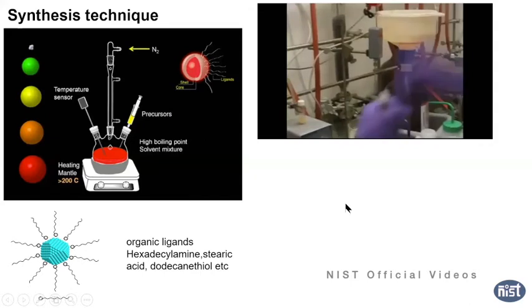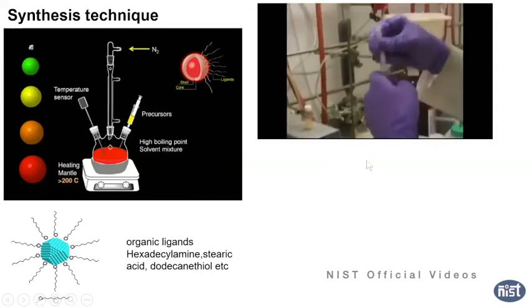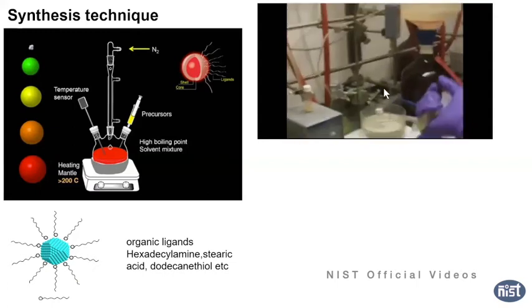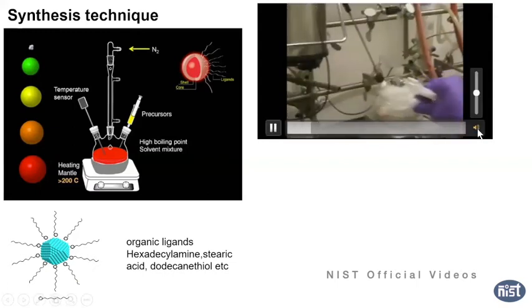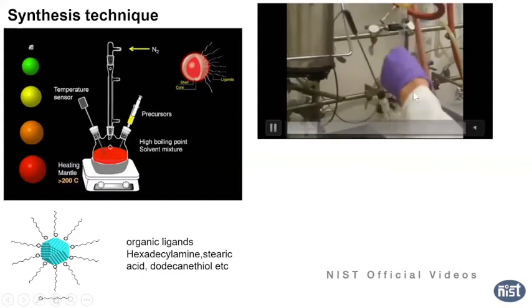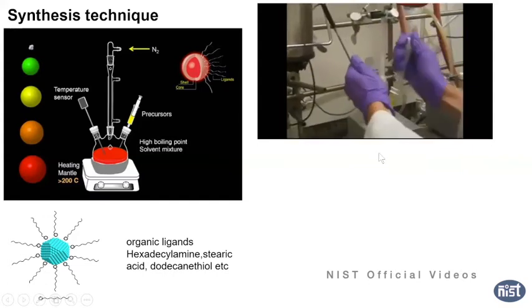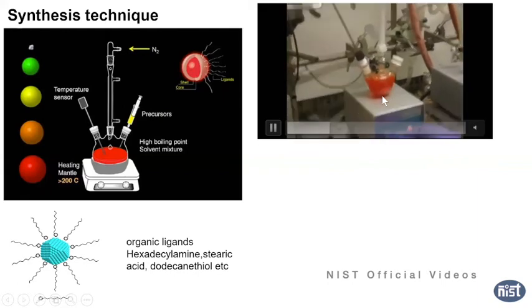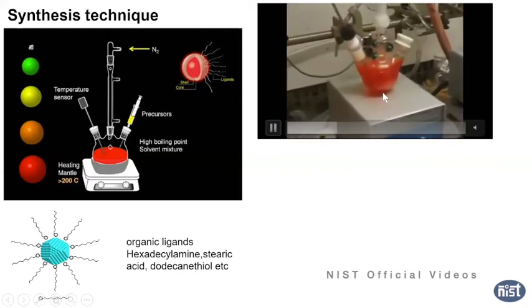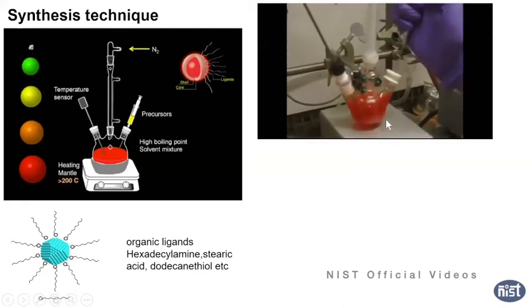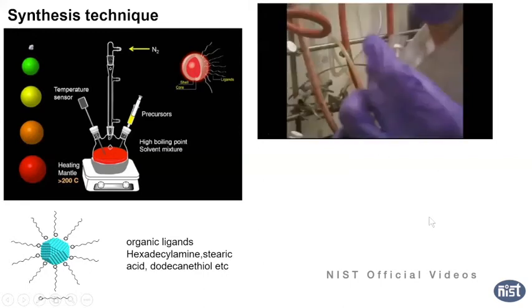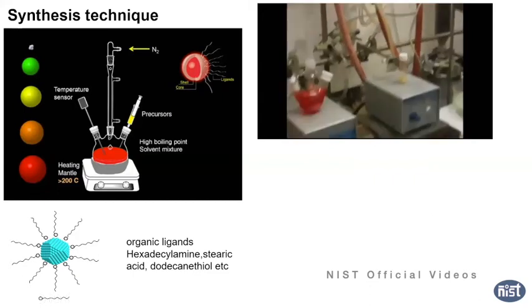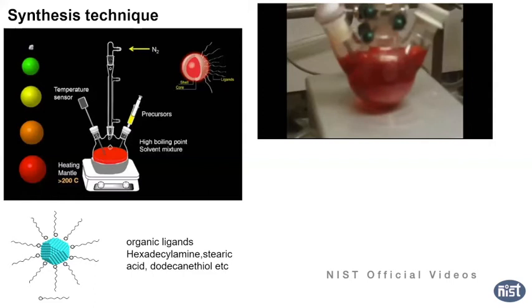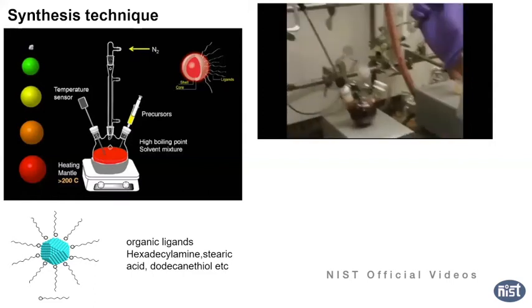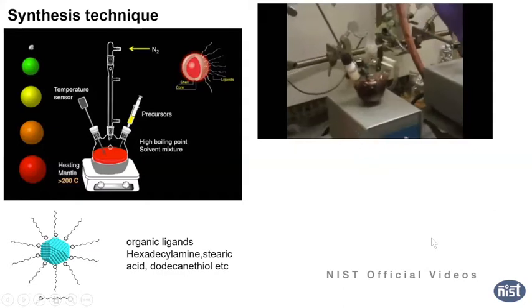And maybe this is one video of how it reacts. You can see the temperature controller. You can inject from here, and you can see the nanocrystal growing, and it's very fine. You can see it glowing inside the solution, and we can take out the solution in a vial here, and you can collect at different time scales, so it can grow to different sizes. And you can see it looks black, but it's not black. It's a very concentrated solution, that's why.